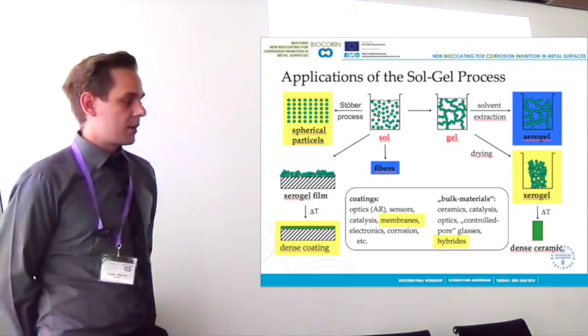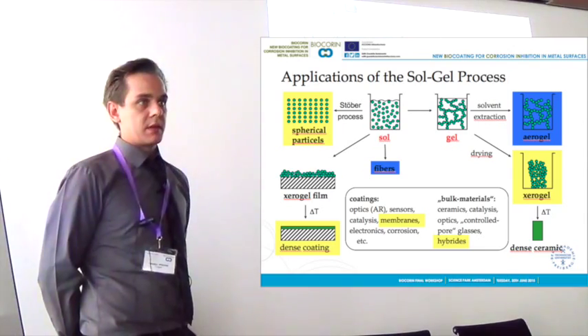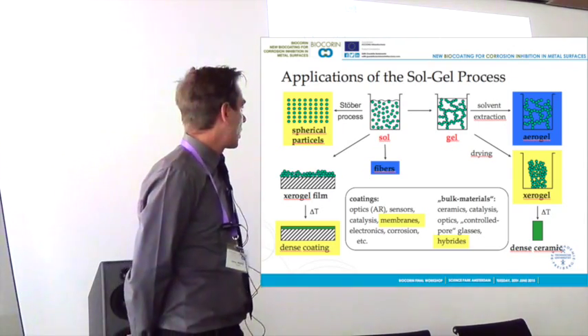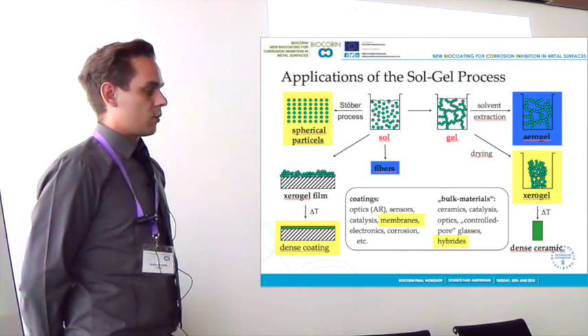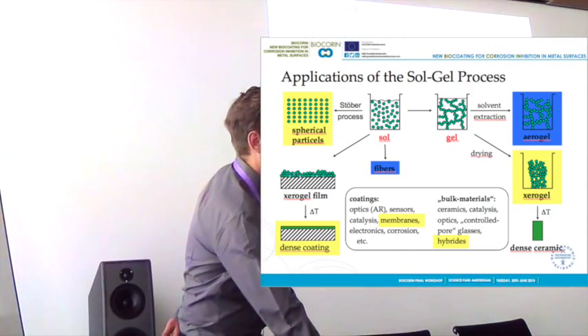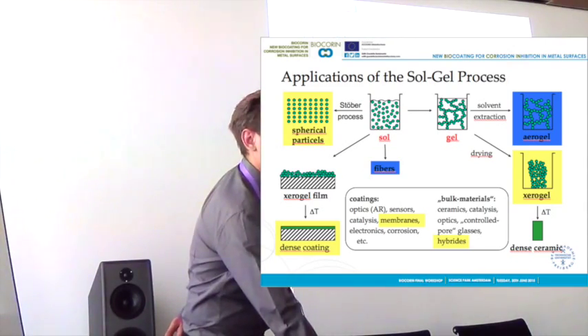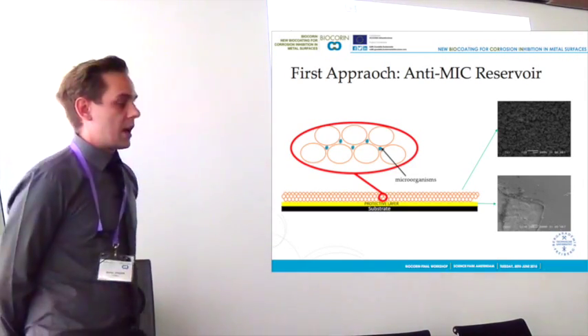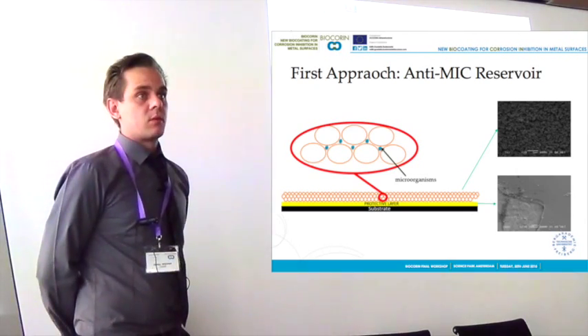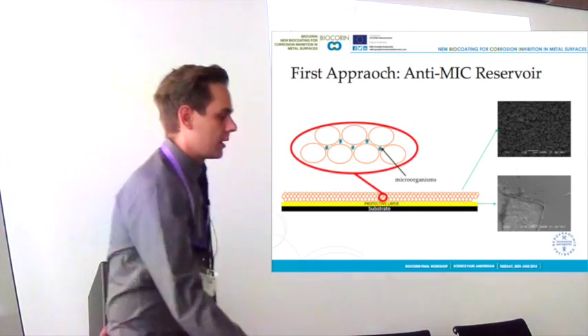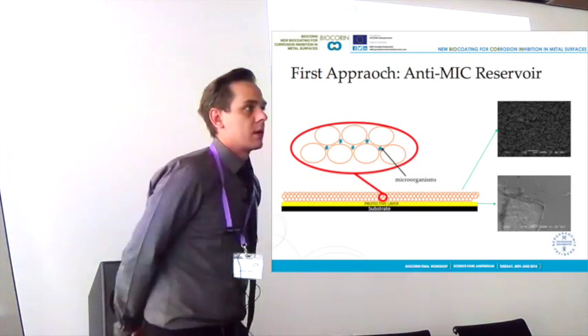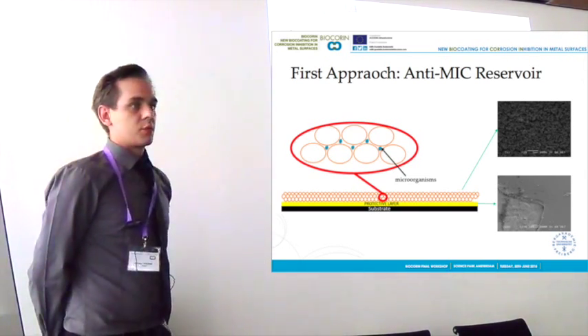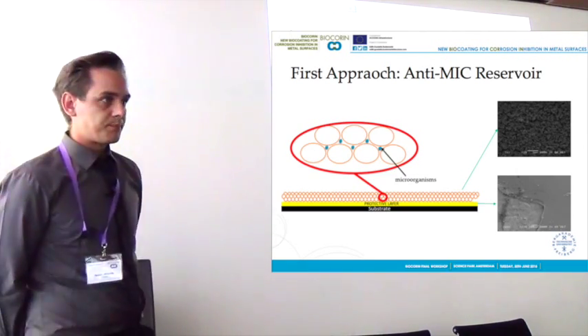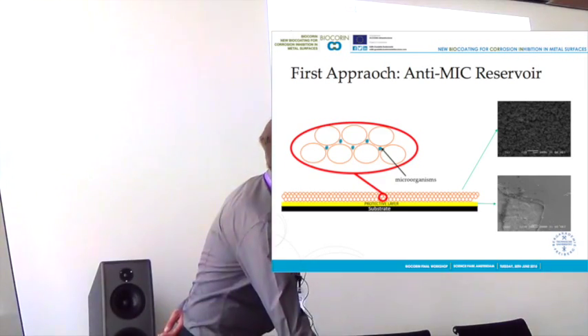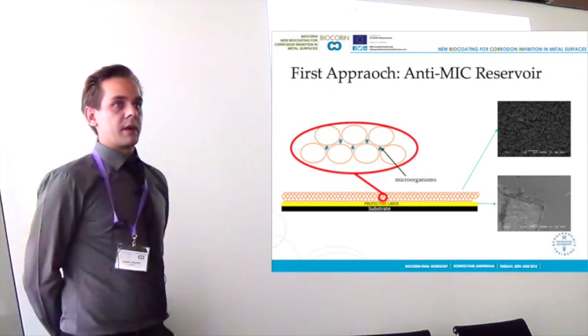Everything starts with the sol. So the sol is formed by hydrolysis and condensation of suitable gel precursors. And what we focused on was the synthesis of spherical particles and of dense coatings. The first approach was designed as an anti-MIC reservoir based on two different coating systems. The first coating is a protective coating based on gel material, and this should protect the steel from corrosion. And a second coating, a porous coating, where we could integrate the microorganisms.